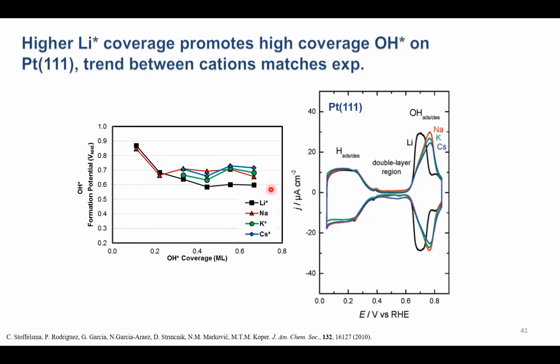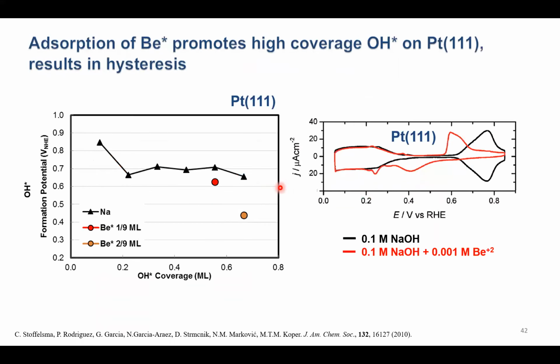Just very briefly, we can also explain some of the identity effects. I won't talk too much about this, but it also comes down to the relative coverage that we can achieve on the surface of these various alkali metal cations. What I think is more exciting, and I want to move on to the last set of results I'd like to talk about here, is looking at a cation that we find interacts so strongly with adsorbed hydroxide on platinum-111 that it actually causes hydroxide island formation on this surface.